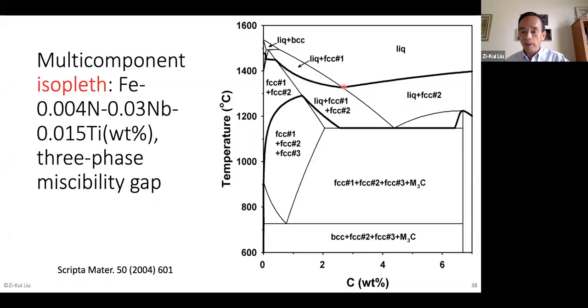You want to go to low carbon here, right? If you go to carbon here, you get in trouble. The carbon has to be lower, okay? And the lowest one could be, you have to actually go here, because in this range, you always form some kind of titanium nitride from the liquid. So you have to control your carbon below this temperature, below this composition, so you can avoid formation of the titanium nitride from the liquid phase.